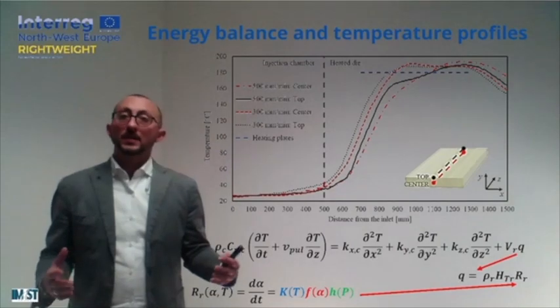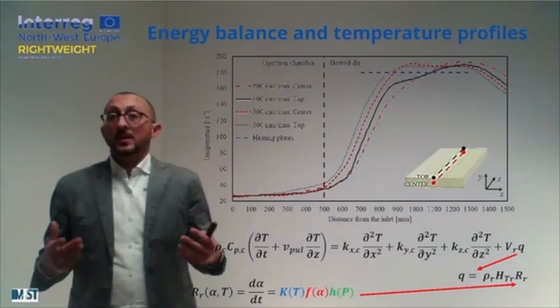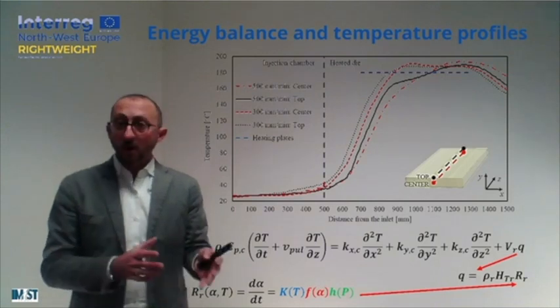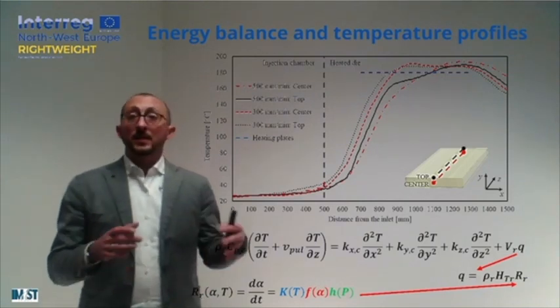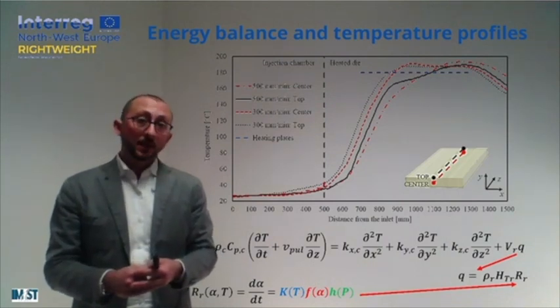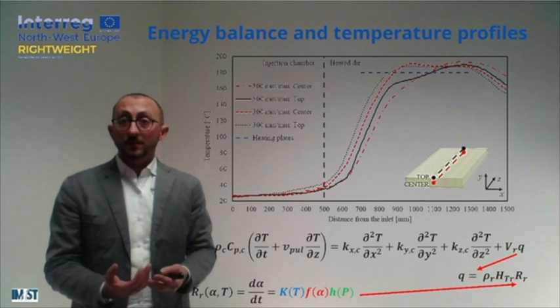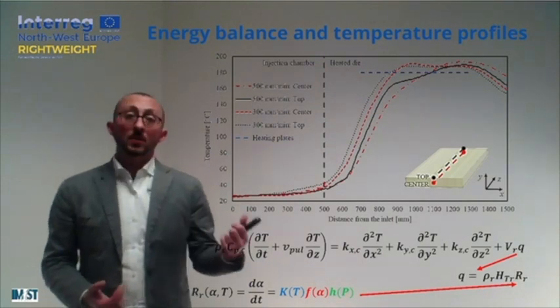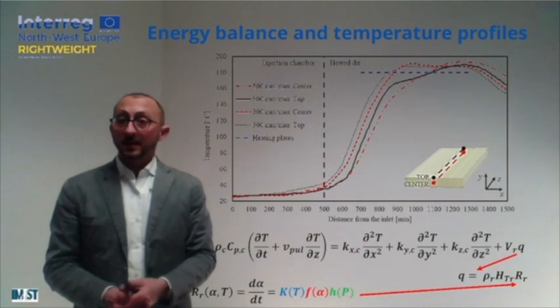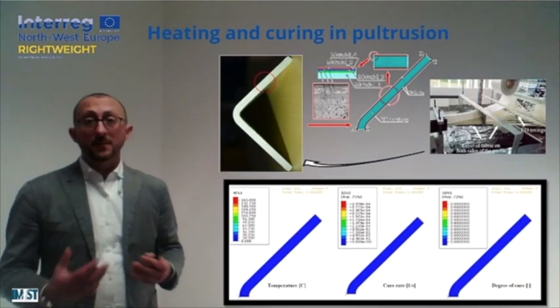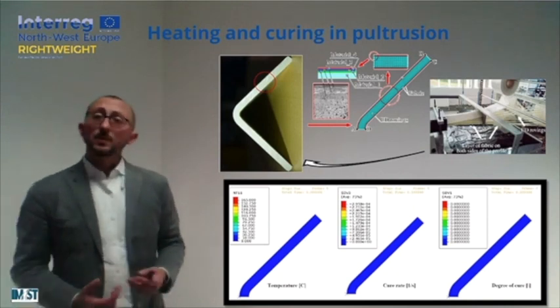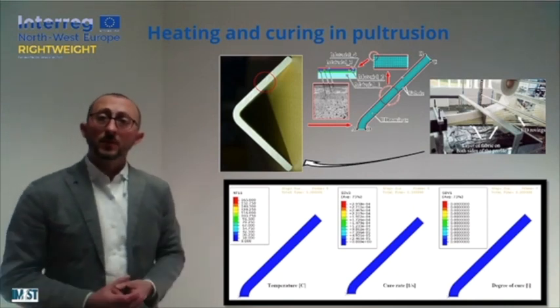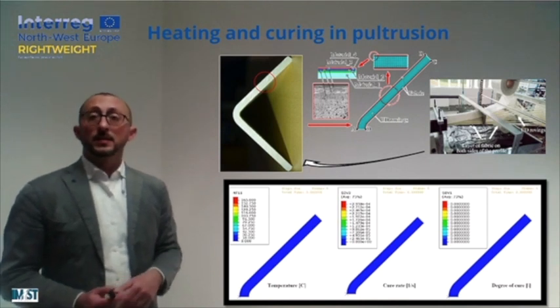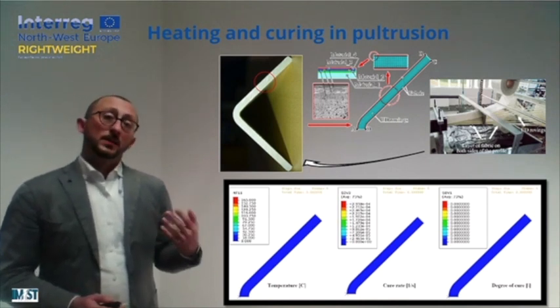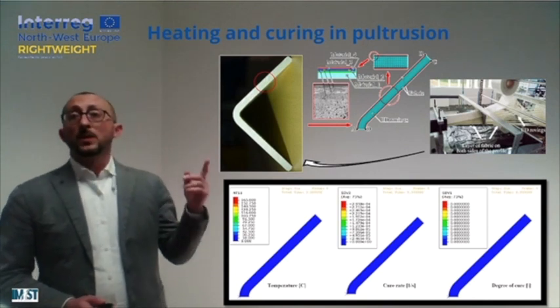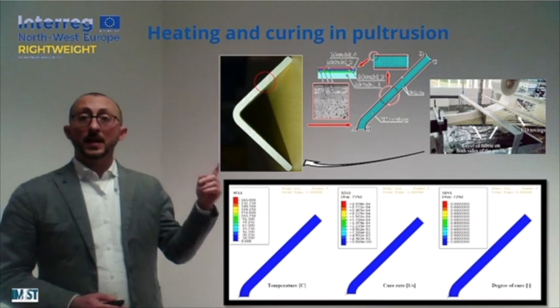It is quite evident that after a while we don't have to increase further the temperature of the heating die. Otherwise, the heat generation inside the material will be the reason for an extreme overheating of our composite, and the resin, of course, will burn and will degrade. Several software packages are suitable to solve this kind of problem, and what I'm going to show you now is the simulation of the temperature and degree of cure looking at this L cross section.